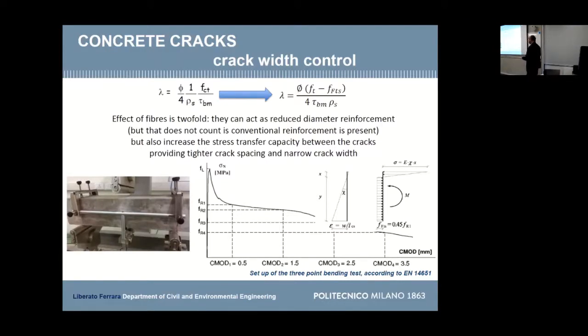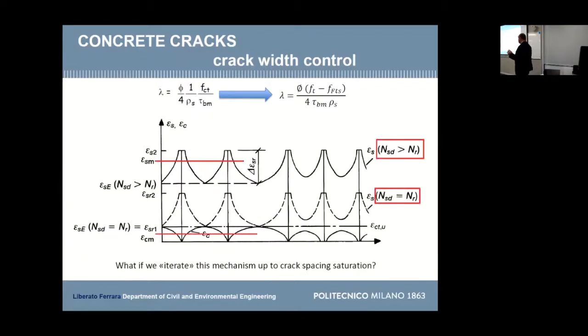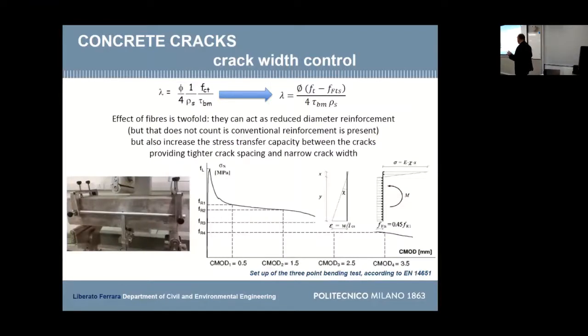And we identify the stresses at different levels of crack opening. In fiber reinforced concrete, we pick up 0.5 millimeter and 2.5 millimeter as relevant crack openings. And if you work out these numbers, you can realize that given the geometry of the specimen, 0.5 millimeters corresponds to an average strain on the cross-section, which is equal to 2 per mil. 2 per mil is more or less the strain at which the conventional reinforcement yields. If you have 400, 500 MPa steel, divide by Young modulus, you have about a yielding strain of 2 per mil. And 2.5 millimeter corresponds to an average strain of 1% of the cross-section, which we can set as a conventional limit for tensile strains in a reinforced concrete cross-section.